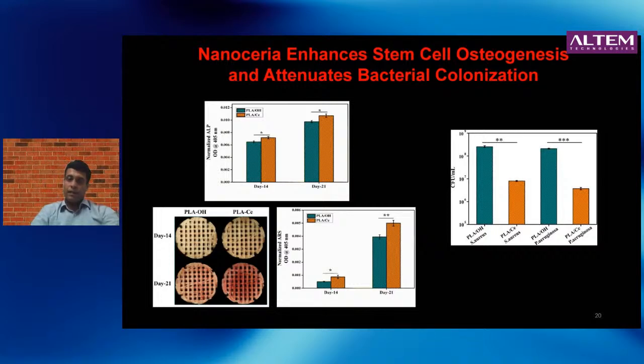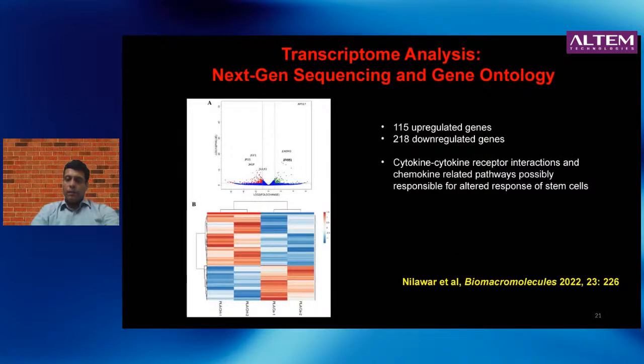And in fact, ROS has another consequence, which is if you actually grow bacteria on these scaffolds, the ones with Ceria can help in reducing the attachment and growth of bacteria by some more than one log order. Okay, so this is important because many of these implants are prone to bacterial colonization and infections. So if you can reduce bacterial infection, that actually helps in improving the bioactivity of the scaffold, and that is actually desired. And lastly, always the question in our mind is, what is happening in the scaffolds or on the scaffolds for the cells that leads to these changes in osteogenesis.